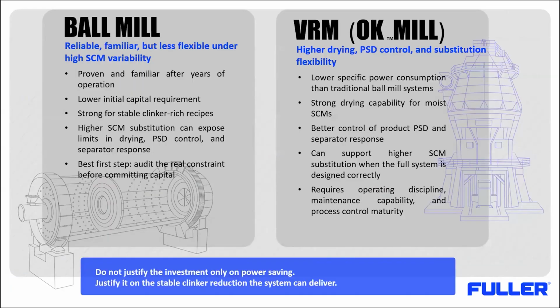At this stage, the investment question is not simply ball mill versus VRM. A ball mill is proven and familiar and often has a lower initial capital requirement. But at higher SCM, the limits can appear in drying capacity, PSD control, and the separator response. A VRM, including the OK mills, can offer lower specific power consumption, stronger drying capacity, and better separator response and better PSD control. But the real point is not energy saving alone.